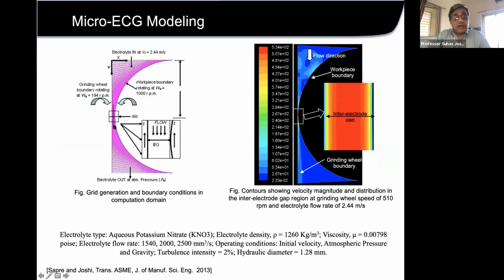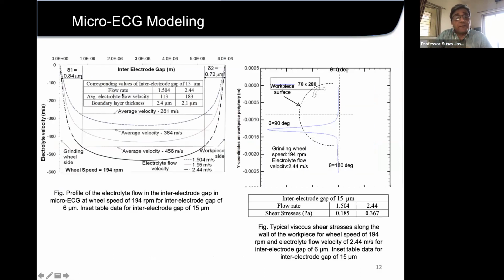At the same time, we did model the very small interelectrode gap, and what happens in this gap, what the velocities are at the two boundaries, and how much stress these boundaries apply on the surfaces. So this was another effort which we did. You can see this is velocity versus the distance across the interelectrode gap. The velocities are higher towards the wheel, and on the workpiece side also the velocities are higher, and they create some kind of shearing stresses, and this is the magnitude of the shearing stresses, which is maximum at 90 degrees.